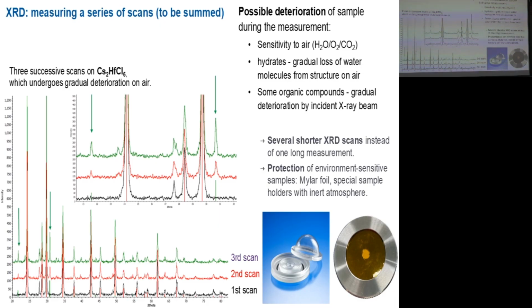Of course, if you are working with some inorganic well-stable materials where the stability is known, you needn't do it, but in certain cases, for example, when you measure some salts of transition metals, not hydrates but anhydrous salts, such samples might be very hygroscopic. So, for example, in this case, we observed that something is happening there, that even some additional phase is arising during the measurement. So you can reveal such processes in the series of scans, and if you reveal that, you can consider some procedure to secure your sample against the air.